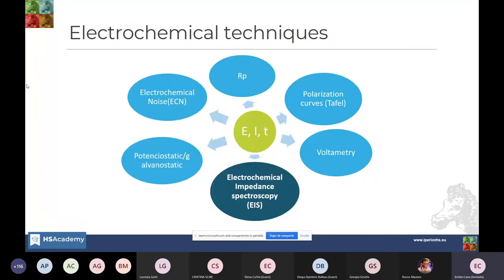You may have noticed that I have said electrochemical techniques in plural, and it is because there are many types or variants of these techniques. In all cases, we are dealing with the same parameters. We are dealing with the voltage, the potential E. We are working with the intensity of the corrosion, I, and we are working with the time. And depending on how we combine these parameters, which ones we control and apply and which one we measure, we have different techniques. We have polarization resistance, polarization curve, voltammetries, potentiostatic or galvanostatic techniques.